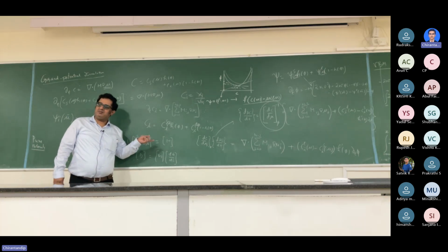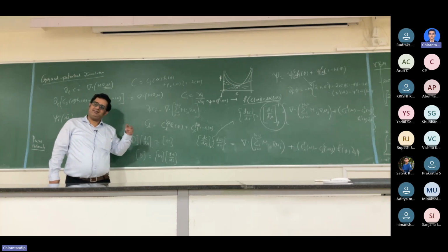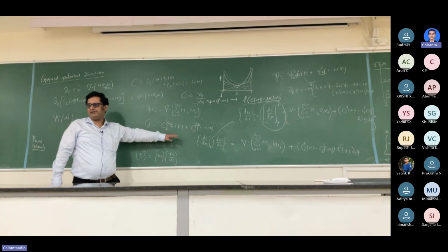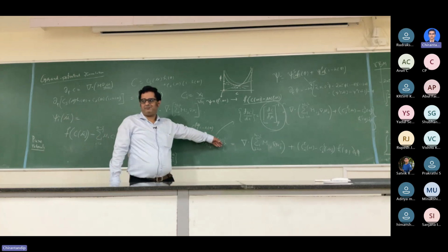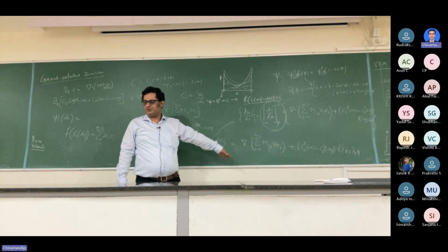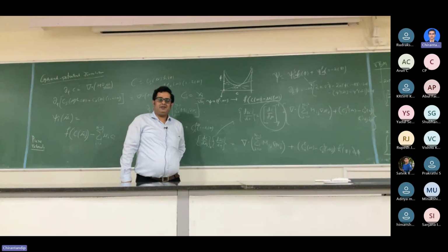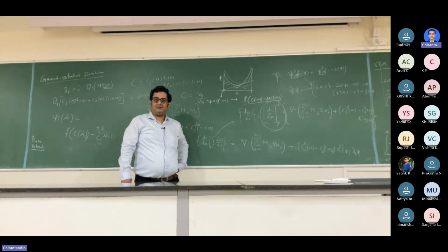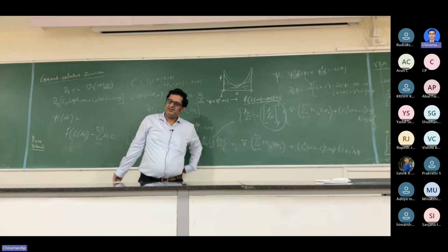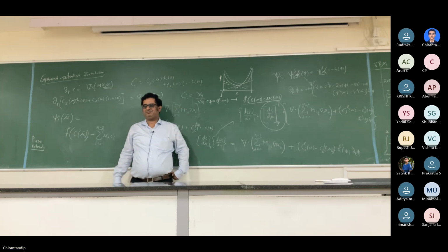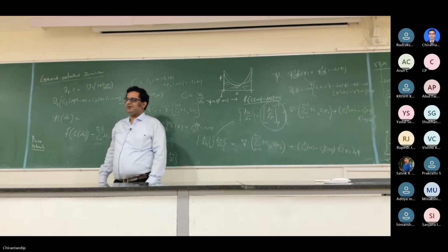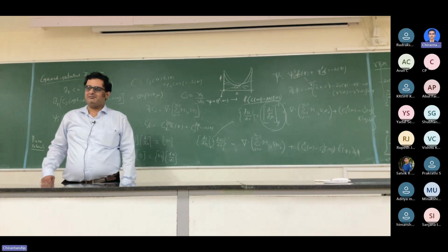Apart from the iterative procedure that you typically have for getting the CS and CL again. You don't have the iterative procedure. Okay. Because the same is directly a function. Right? So you have gotten rid of a very costly iterative procedure. That cost of the iteration actually goes up as the number of components go. You gain in memory and gain in effectiveness.